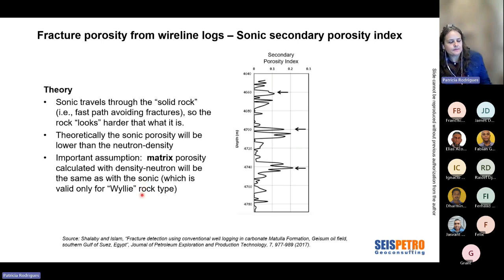And what I mean by that is, I would say, this is valid, and I have seen it working only when you have a pure limestone, so you just have only one mineral. When you calculate a neutron density porosity in a limestone matrix, you have a really good porosity. And when you calculate the porosity from sonic, you know exactly the delta T, or the slowness, of your matrix. So in areas where there are no fractures, you're going to see an overlap.